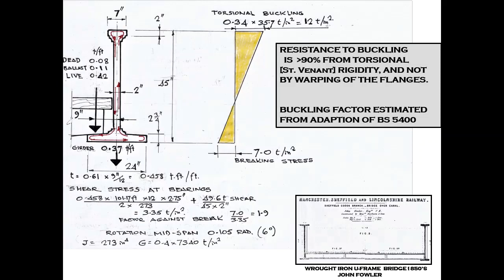Now, what about the buckling resistance? The resistance of a cast iron member with thick webs and flanges largely depends on the St. Venant rigidity, that is the internal shear stress resistance, rather than by warping of the flanges, which is how bridges of U-frame type, you can see on the bottom right, of that type using wrought iron or steel, the capacity of the top flange is really a question of the flange acting as a strut, which is restrained by the U-frame rigidity of the bridge, with the cross girders and plan stability by continuous flooring. None of that was present in this bridge, so the only way it could obtain its torsional resistance is by the internal shear stresses. Thus, the width of the top flange doesn't really come into it too much.